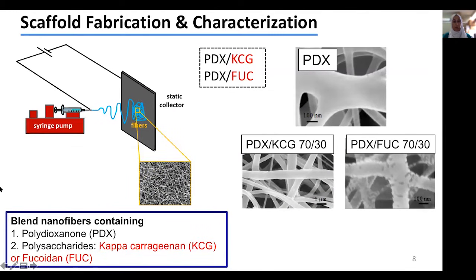So in the first part of our study, we fabricated blend nanofibers consisting of a seaweed-based polymer in combination with a biodegradable polymer, which in this case is polydioxanone, here abbreviated as PDX. We were mainly concerned with two different types of seaweeds, namely red seaweeds and brown seaweeds. From the red seaweeds, we extracted the polymer kappa-carrageenan, which will be abbreviated as KCG in the next slides. And from the brown seaweeds, we extracted fucoidan, which is abbreviated as FUC.